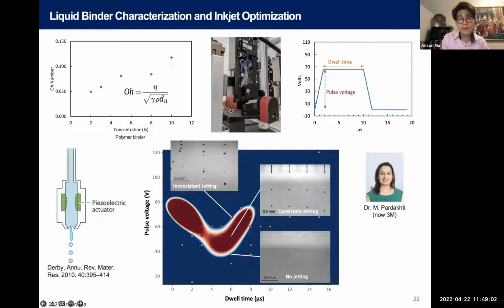One thing we do that is a little more sophisticated: in addition to calculating the Ohnesorge number, the dimensionless viscosity, we also set up the drop watcher system, and then we can do experiments and map out under what condition, for this particular ink formulation, we have a consistent jetting zone. These are two process parameters in the piezoelectric inkjet print heads, and you can treat them as process parameter 1 and process parameter 2. By doing various experiments, you can map out the condition to successfully jet the material, in addition to just knowing the Ohnesorge number or the dimensionless viscosity.